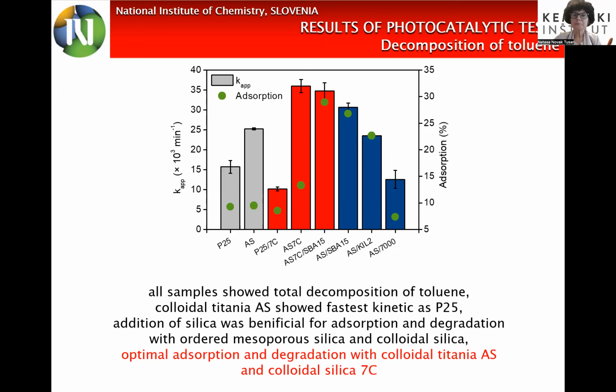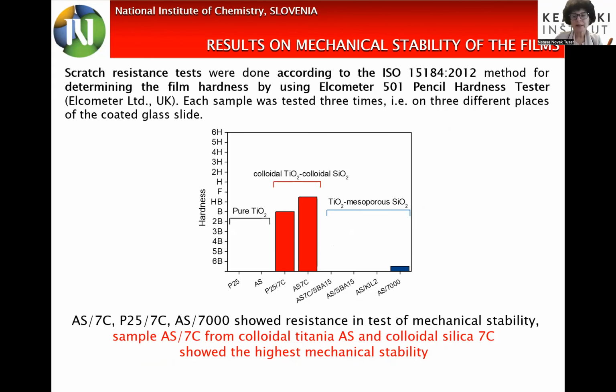And actually, if we look at the comparison of only commercial titania or the combination of other commercial titania with silica, we can see that this is really the optimal option. And if we look further at mechanical stability, we can see that for the materials with colloidal silica we have the best mechanical stability. So here we also have P25 with colloidal silica. It has a little bit lower mechanical stability, but with colloidal titania we have the highest mechanical stability. And that was also the goal we wanted to achieve.